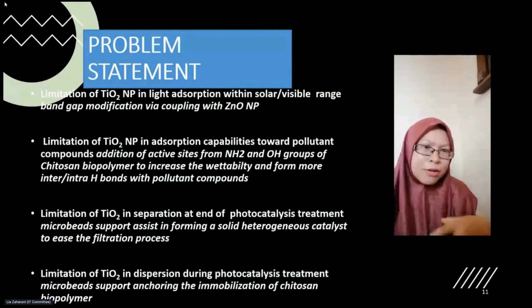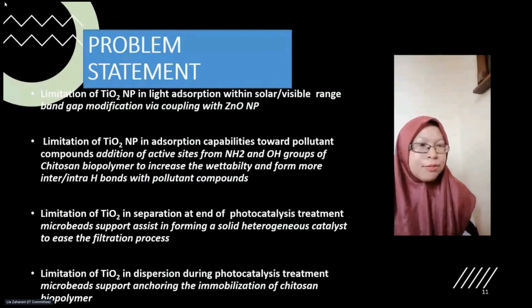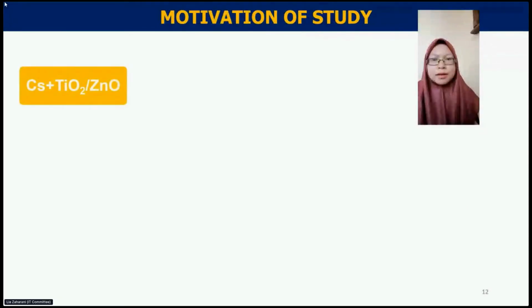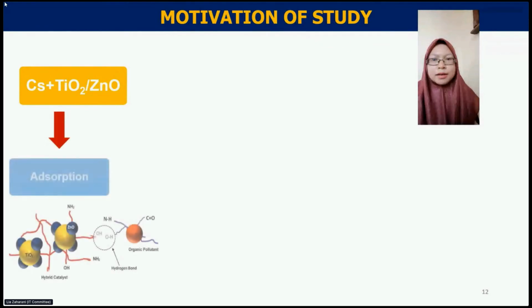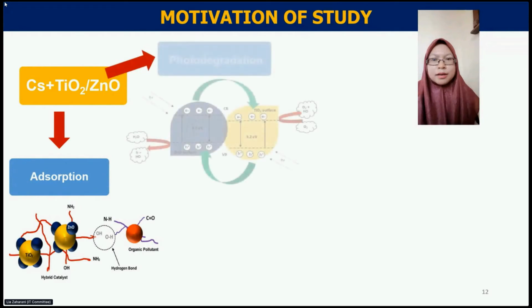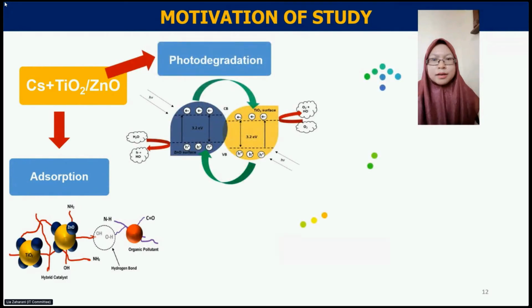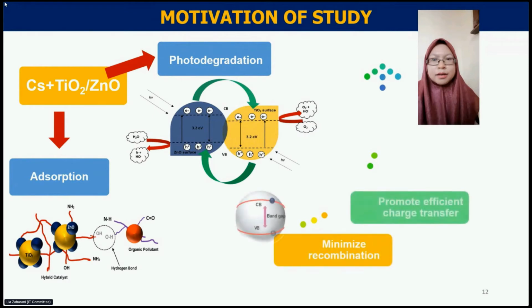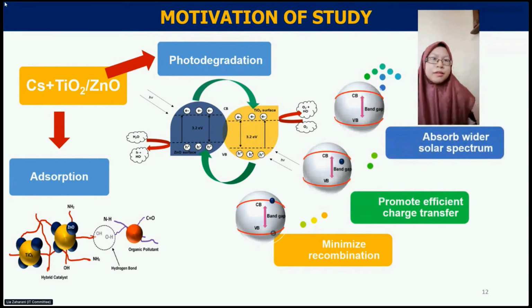The immobilization of the catalyst has brought increasing interest to the study of polymer-based composites, whose porosity and pore size can be controlled. This research provides a simple and readily accessible route to the formation of the ternary titanium oxide, zinc oxide, and chitosan, which overcomes the charge recombination and separation limitations of the native titanium oxide. The modification allowed the titanium oxide to be photocatalytic under visible light sources.